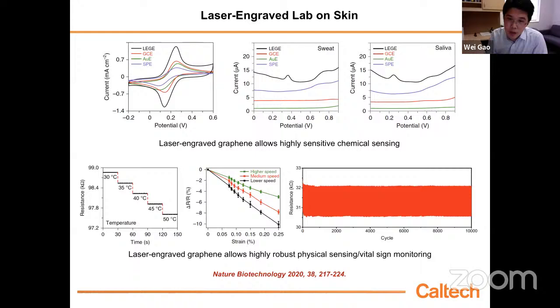Look at this bottom right figure. We do repetitive bending using a robotic arm for 10,000 cycles. The resistance of this graphene structure remains very stable. That means they are still quite robust for long-term operation.